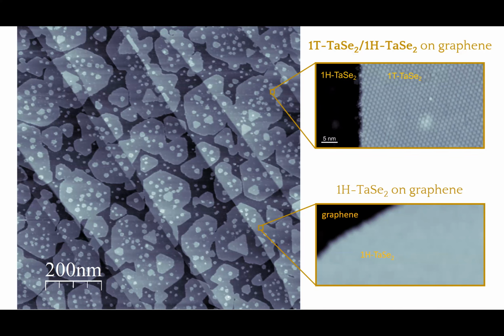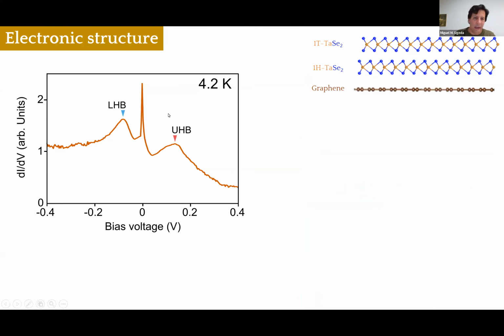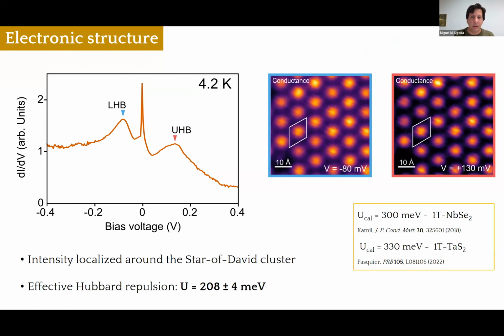But once you get this kind of sample, you can look at these bilayers. And here I show you a typical dI/dV spectrum taken on one of these bilayers. Let me remind you that dI/dV is proportional to the local density of states. So we observe 3 different peaks, 2 broad ones and a sharp one at the Fermi level. On this occasion, we identified these 2 broad peaks as the lower Hubbard band and the upper Hubbard band. And the reason is twofold.